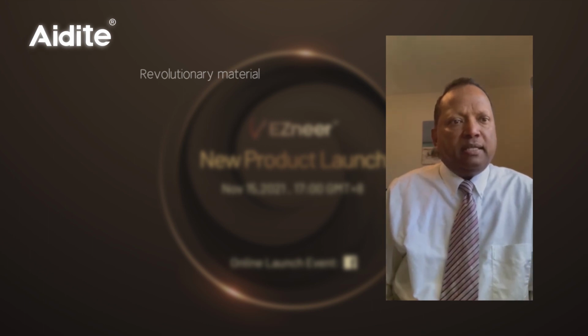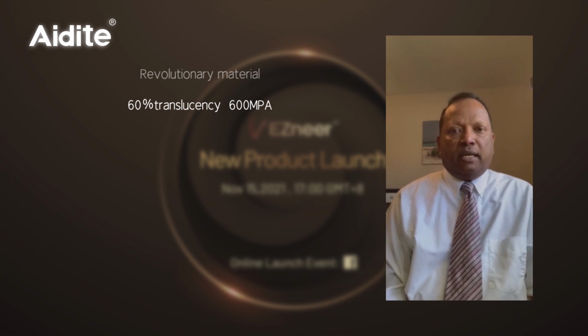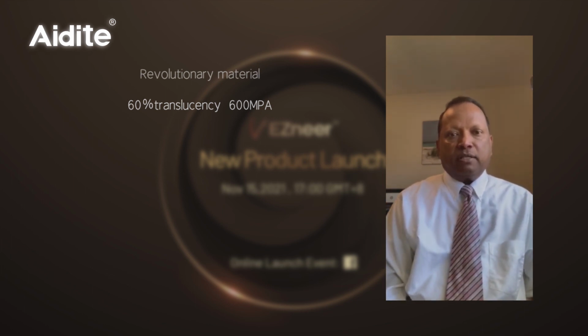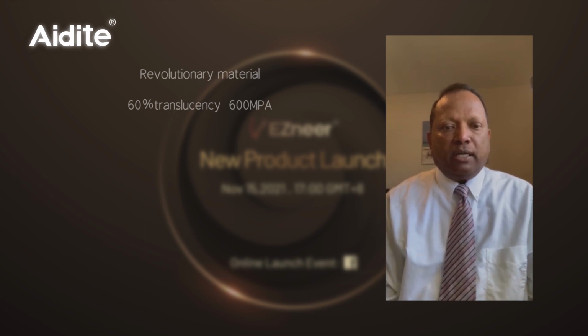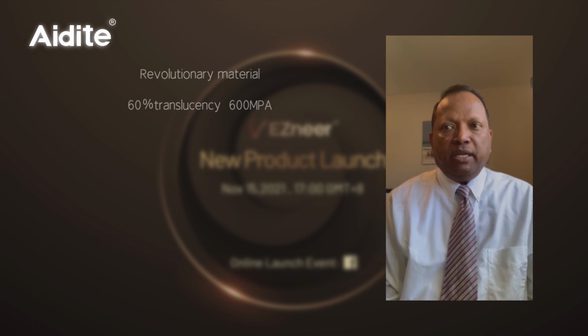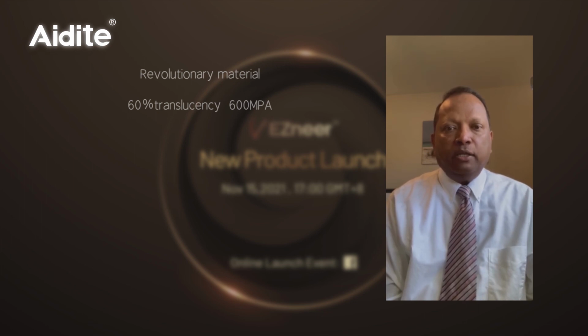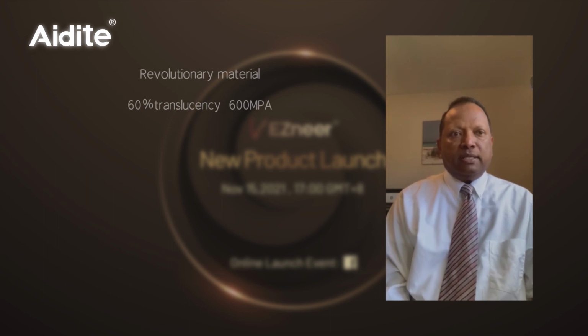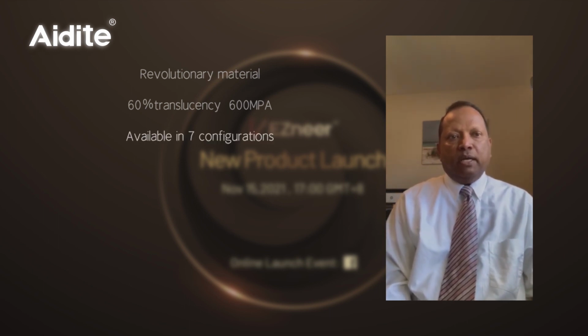So it has 60% translucency with 600 MPa of flexural strength, and this is very ideal for thinner veneers. Applications can be as thin as 0.2 millimeters to 0.3 millimeters, and it can also be used for no prep veneers. This is available in 7 configurations. You can have choices in bleach shades, multi-layer, and value shades. So basically, you can cover the entire range of patient situations, whether you want to cover dark understructures or just make some very beautiful aesthetic veneers.